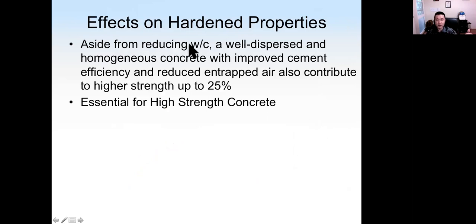So besides reducing the water cement ratio, a well dispersed and more homogeneous concrete can actually improve the cement efficiency and reduce the entrapped air, which is the big air bubbles in concrete, which can significantly reduce the strength. So that function itself can increase the strength by up to 25%, without changing the water cement ratio. By adding these chemicals, we can make the concrete more homogeneous, so that can make the concrete have higher strength. Remember, superplasticizer is essential. It's a must for high strength concrete.